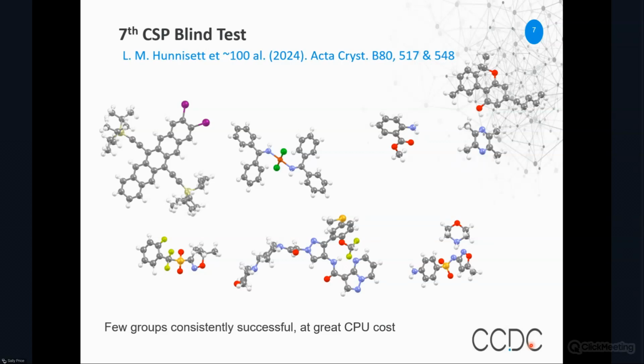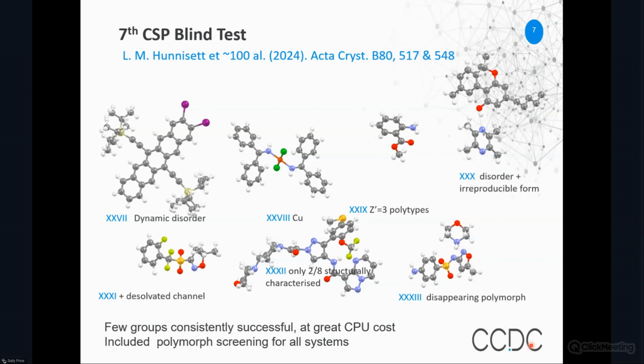And if you ask me who was the winner, I think it was the molecules, because they had actually done and commissioned experimental polymorphic screening on all the systems in the blind test. And virtually all of them came out with a polymorph that was outside the model that we use for crystal structure prediction, with quite a lot of problems of disorder and also some disappearing polymorphs that couldn't be reproduced. So things are advancing, but the experiments and the molecules are also moving forward very rapidly.